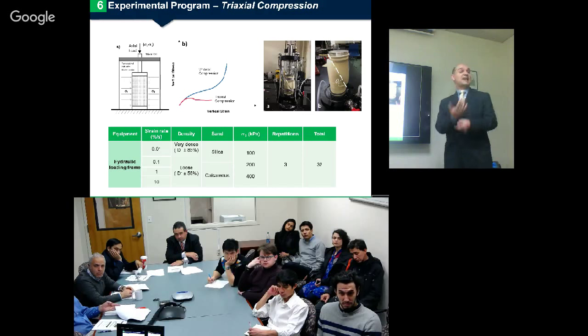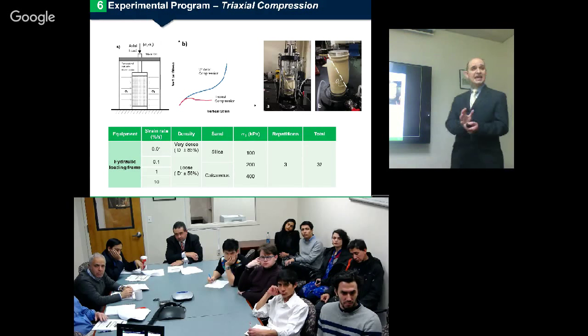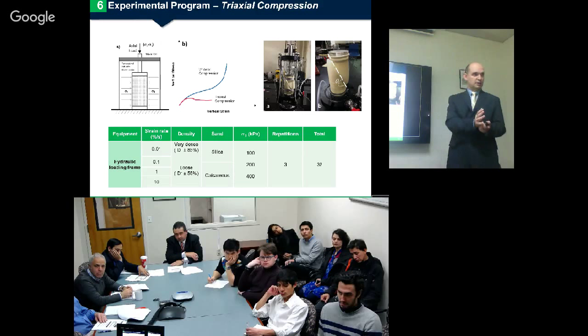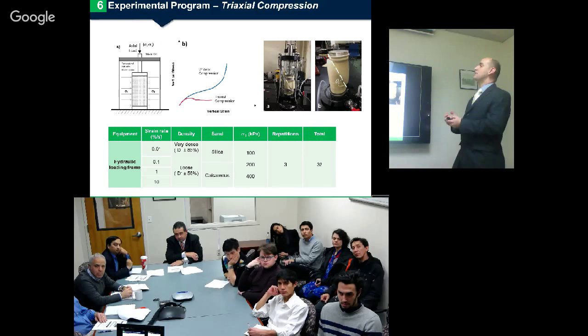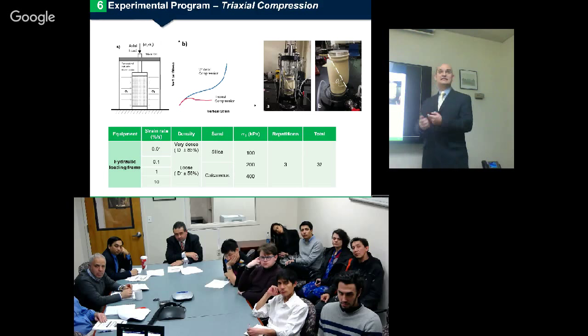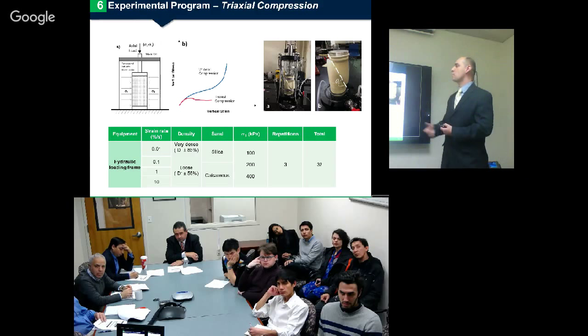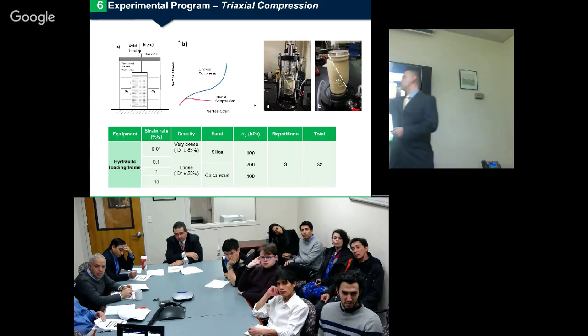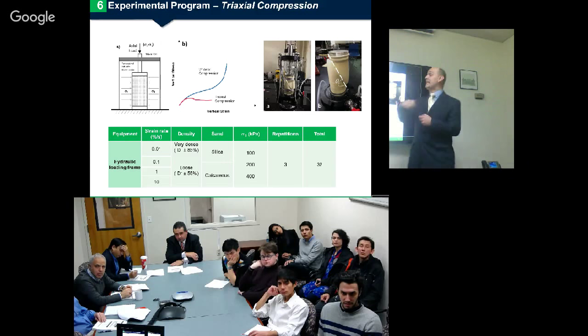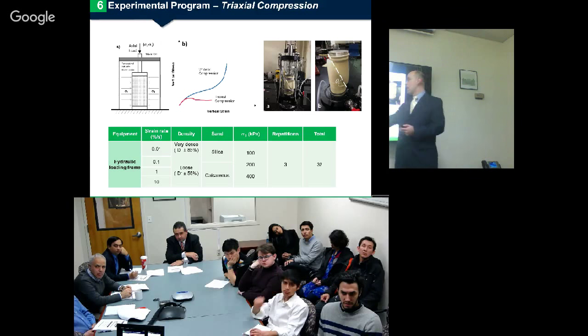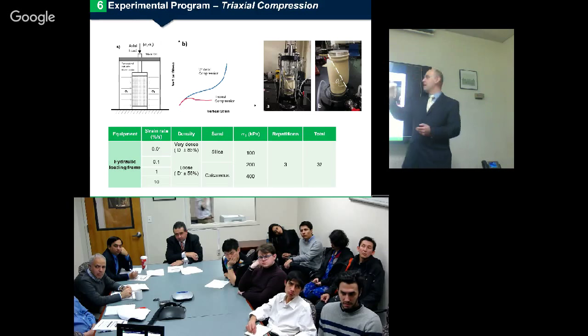Now, for the triaxial compression test, the same loading mechanism is used, with hydraulic actuators. The main difference, obviously, is that we don't prevent radial deformation. We allow it to take place. If you can see the difference, ideally, in triaxial compression we expect a failure of the material as a whole. After the peak is reached, the material is going to experience a critical state or ultimate stress somewhere here.